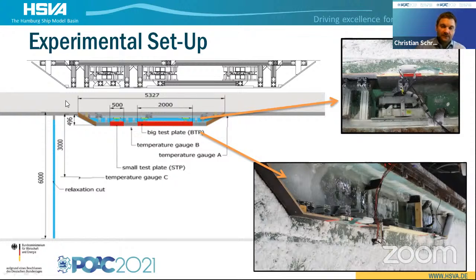So in the end, the whole test setup is a little bit of an extension of the basin sidewall with 2 different test plates to measure the pressure forces of the ice. During the freezing phase and before the testing, we always removed the ice behind the measurement setup so that there are no force chains in between the sidewalls and the measurement setup itself.